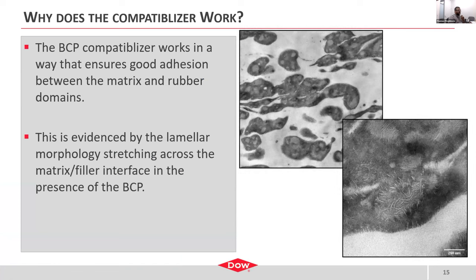So you may ask, well, why does it work? And we can analyze this using transmission electron microscopy. The reason that these materials work is because the block copolymer ensures the adhesion between the matrix and rubber domains. What's shown on the right are two transmission electron micrographs of these TPO materials, where you have the polypropylene matrix, which is the bright white material, and the polyethylene rubber, which is the darker material. And you can see in these darker domains, there are domains of polypropylene, the brighter domains in those darker domains.